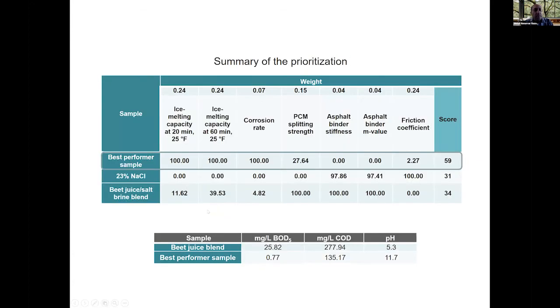So we came up with the best performer sample that showed the highest score in terms of ice melting capacity, corrosion rate, splitting, the impact on the splitting strength of the Portland cement mortar, and impact on asphalt binder stiffness, asphalt binder M value, and also in terms of friction coefficient. So, in the next step, we examined the BOD, which is the biochemical oxygen demand. BOD 5 means after 5 days of experiment, and COD, which is chemical oxygen demand of this deicer.